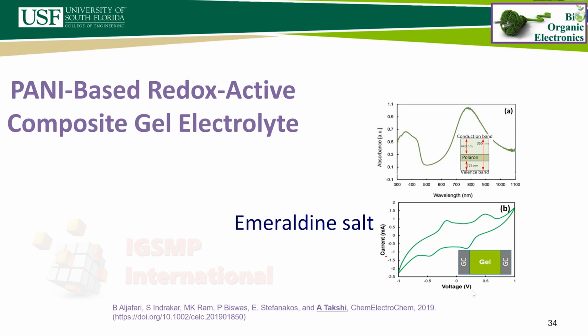So this is really interesting, especially after Dr. Zhang's talk, where we were talking about how we need to disperse molecules or nanoparticles inside the volume of the material. You can imagine that if we go beyond the percolation effect, there would be a short circuit between the 2 electrodes. But if you keep the level of the nanoparticles, in this case conducting polymers, low enough that they are not necessarily connecting the 2 electrodes, we have a medium where we can use their properties, such as energy storage.